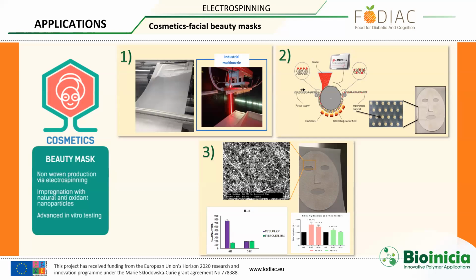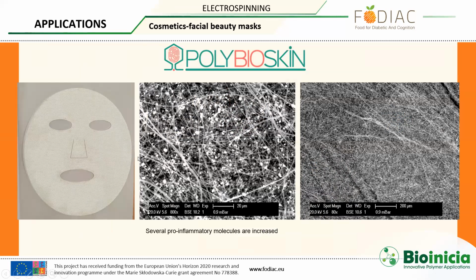In this particular case that we are going to show here, Bioinicia took part in mass producing the carrier. And then there was another company who took care of impregnating the complex that we used, which was chitosan complexes. So we did the white part of the mask, and then the other company impregnated these complexes, as you can see in the small dots here. And with the SEM, you will see that the different small particles have been homogeneously distributed within the fibers that we made at Bioinicia.